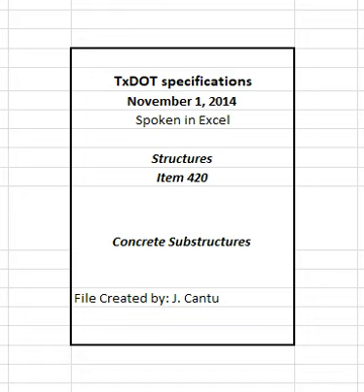Use additional covering, insulated forms, or other means and, if necessary, supplement the covering with artificial heating. Avoid applying heat directly to concrete surfaces. Cure as specified in Section 420.4.10, curing concrete, during this period until all requirements for curing have been satisfied. Have all necessary heating and covering material ready for use before permission is granted to begin placement when impending weather conditions indicate the possible need for temperature protection.